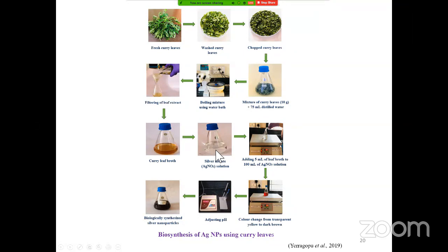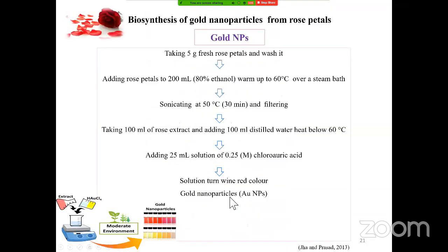And 5 ml of leaf broth has been added to 100 ml of AgNO3 solution, and kept on a rectangular hot plate until the color changes from transparent yellow to dark brown, which indicates the formation of silver nanoparticles. I adjusted the pH to get the proper size of nanoparticle, and we get biologically synthesized silver nanoparticles from curry leaves. And coming to biosynthesis of gold nanoparticles from rose petals,